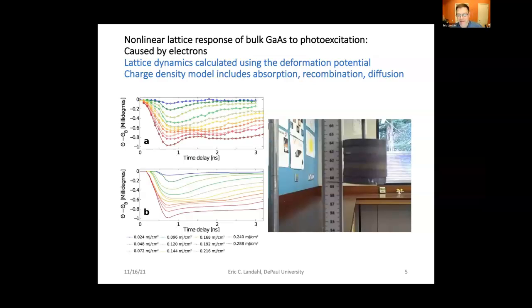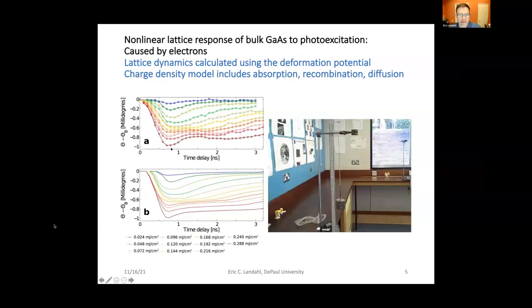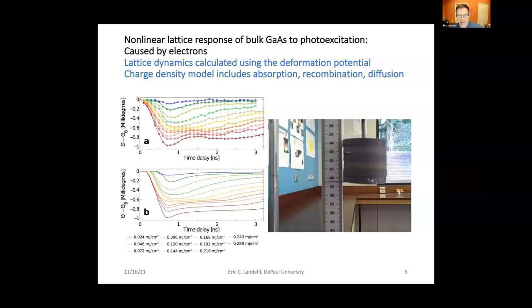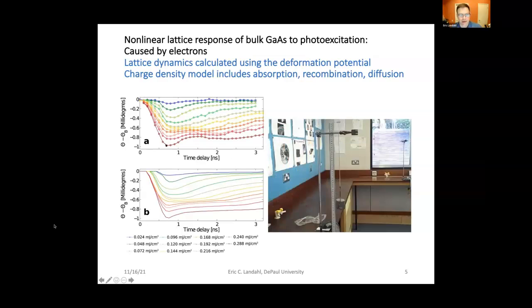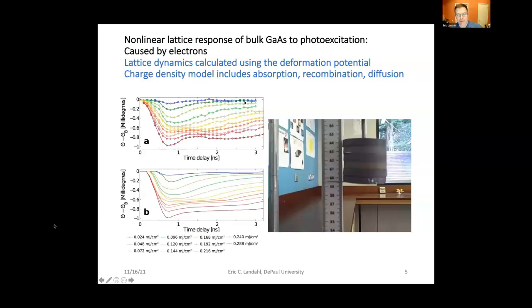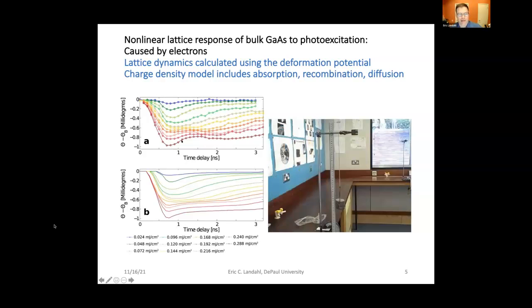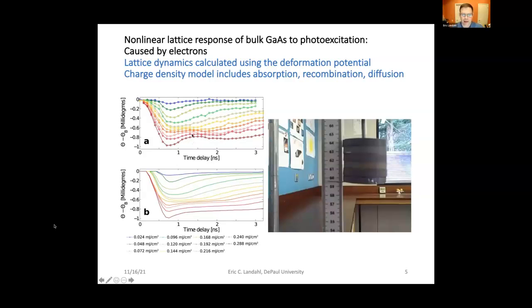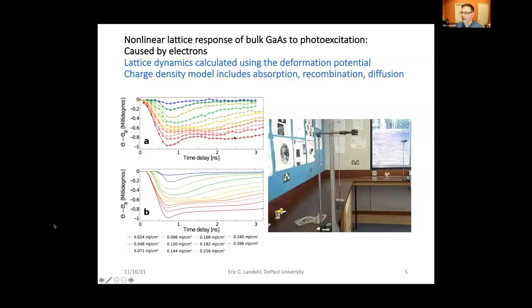There it goes. And so it's generally, rather than just looking at a single time point, which would be the location of the maximum strain, what we showed in the previous slide was just shy of 1 nanosecond. Here we actually measure out the full set of dynamics at the different laser fluences going from low to high, and we find that the strain persists longer. It has a different recovery shape, and even the onset of some oscillations, which are also an indication of non-uniformities perhaps starting to occur within the sample.